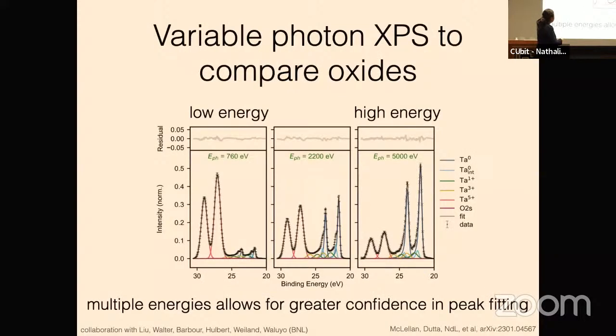So in order to build up this profile, this is an example of looking at the tantalum peak. So at very low energies, these two peaks are the oxide, these peaks up here are the metal, so you can see you mostly see oxide. And then at high energies, you mostly see metal. So this is showing the changes in depth. And okay, so there's a lot of peaks under here that all correspond to different chemical states of the tantalum. And I was a real XPS skeptic going into this project because there's just a mess down here. And then the question is, how do you know that it's like 4 peaks and not 8 peaks or 6 peaks? And how do you know where they are? And the nice thing about this variable photon XPS is that you can fit your entire data set simultaneously and then get a lot more confidence that you have the correct number of peaks, right?